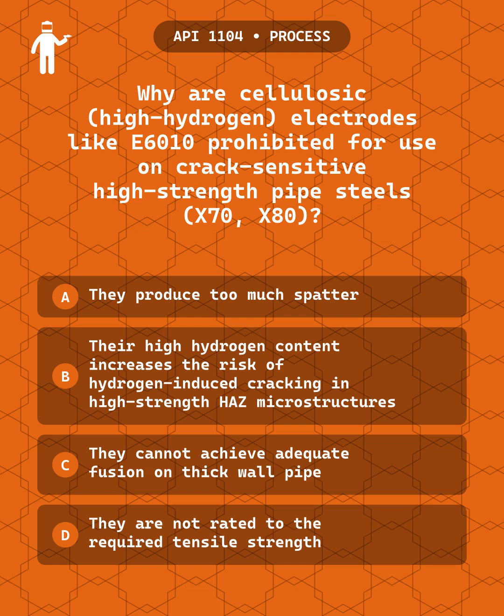Question 9. Why are cellulosic high-hydrogen electrodes like E6010 prohibited on crack-sensitive high-strength pipe steels like X70 and X80? A. They produce too much spatter. B. Their high hydrogen content increases the risk of hydrogen-induced cracking in high-strength HAZ microstructures. C. They can't achieve adequate fusion on thick wall pipe. Or D. They're not rated to the required tensile strength.